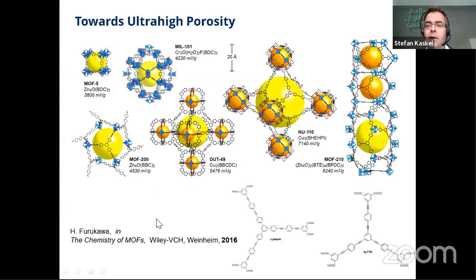And of course, this does not help you in doing all the very systematic work in analyzing the structure of the metal organic framework and recording isotherms in order to analyze carefully the adsorption properties. And over the many recent years, people have tried to improve and enhance the adsorption capacity of MOFs further and further. And these are just a few examples in this direction. For example, from Omar Yaghi's group, the MOF 210, reaching above 6,000 square meters per gram. Then the NU110 from Omar Farha and Joe Hupp in Northwestern University, reaching over 7,000 square meters per gram. Then the DUT49 from our group, reaching more than 5,000 square meters per gram.